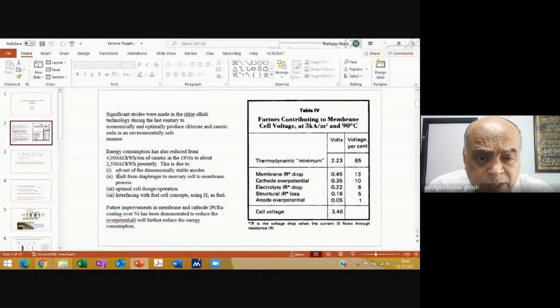And some of them I'd already mentioned, like the advent of the dimensionally stable anodes in the 60s. That's why in the 50s it was much higher. But the moment those valve metal oxides coated on titanium were invented, it made a huge difference because your carbon anode was not corroding anymore. It was a different anode. So that was very important.